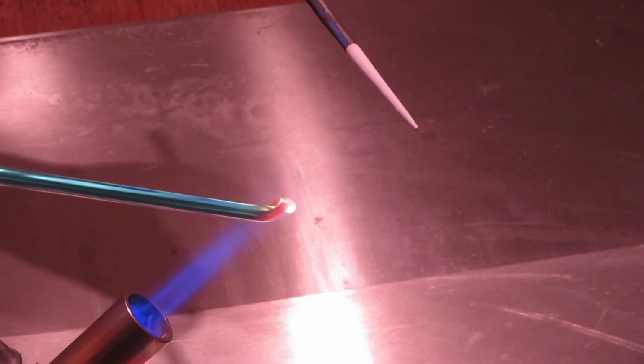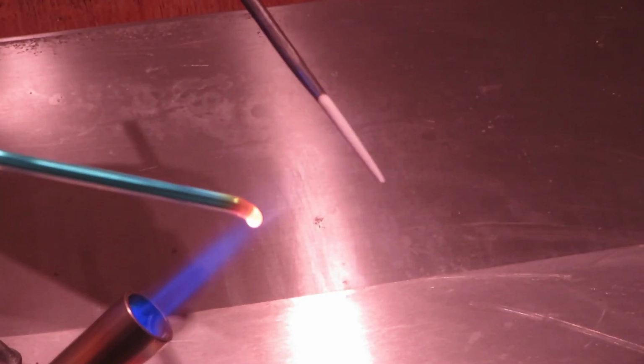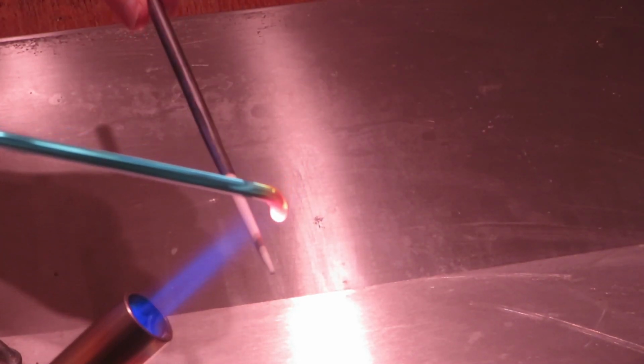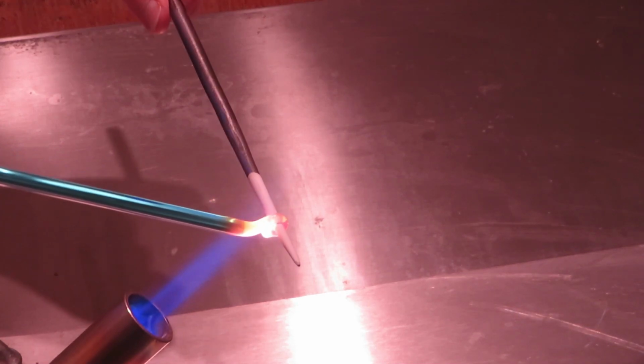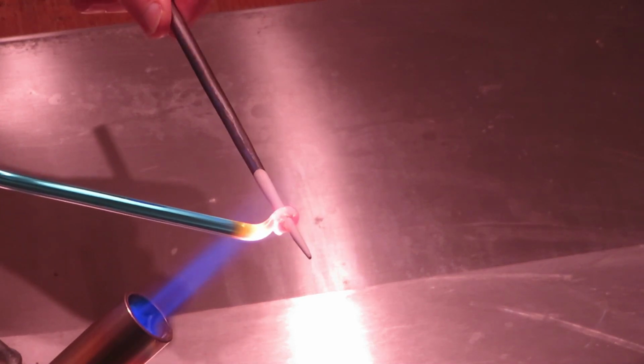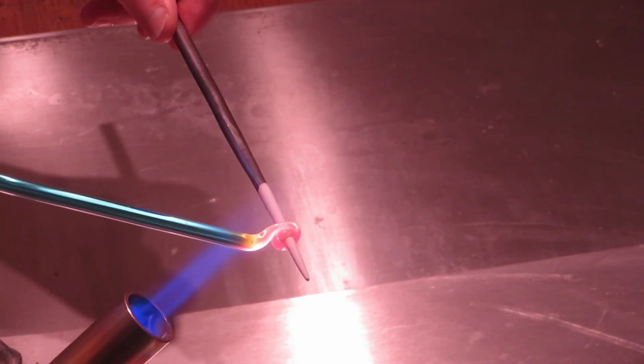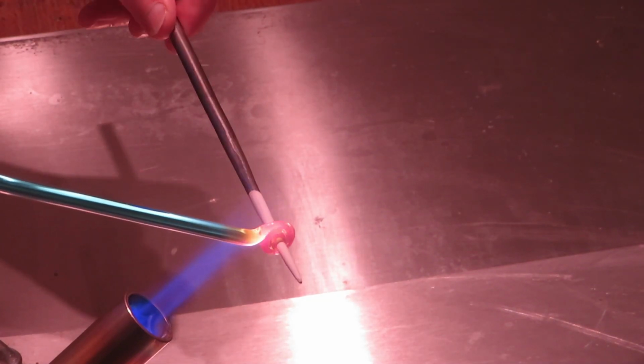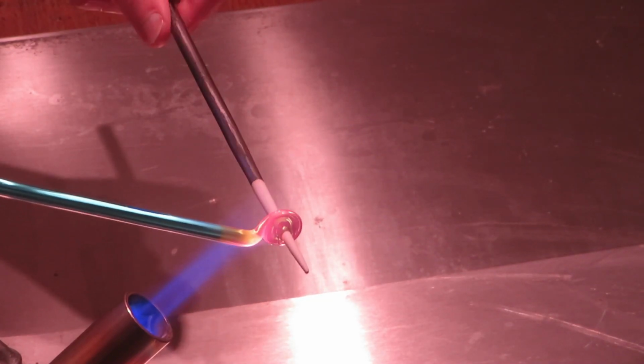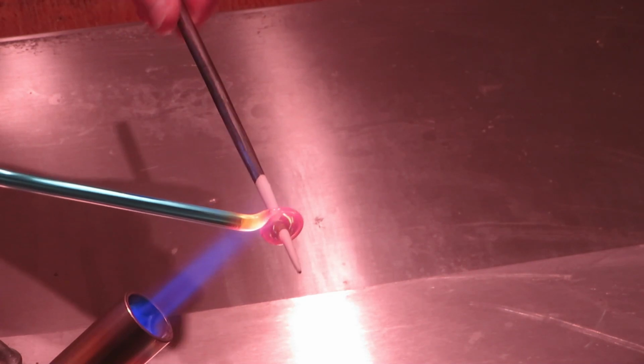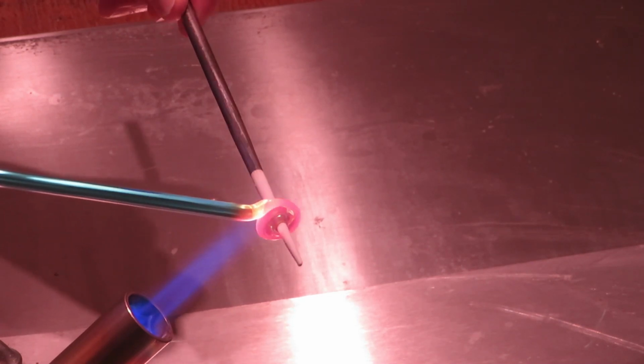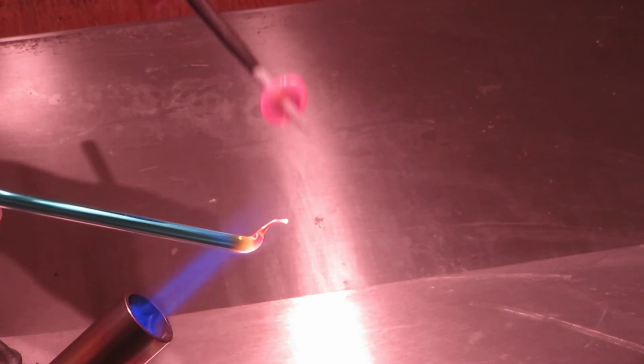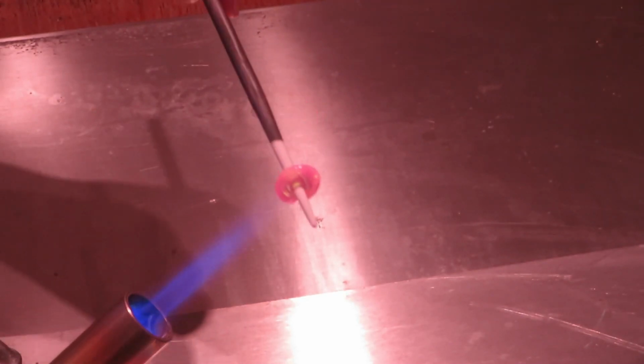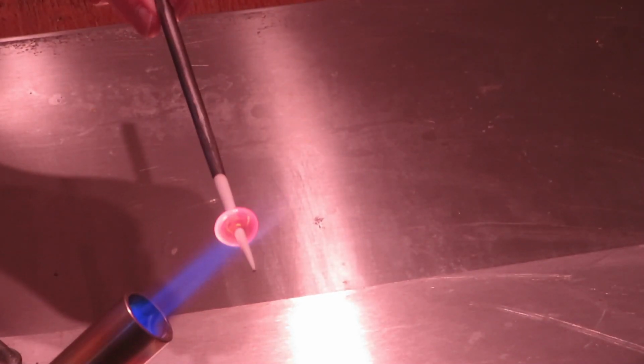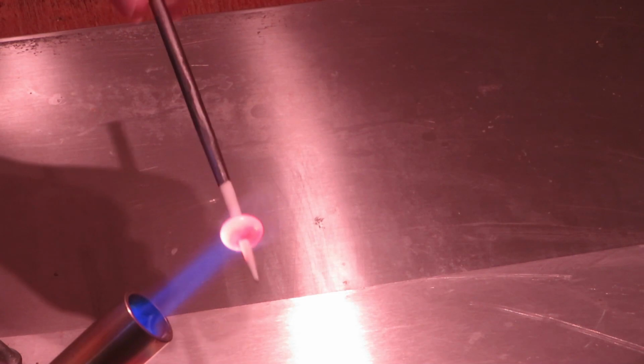Here is a simple bead being made. The mandrel is coated with clay slip so that the bead can be removed easily when cooled. The end of the glass rod is heated until it melts, and the hot glass is wound round the mandrel to make the bead. It is then heated in the flame and forms a perfect round shape.